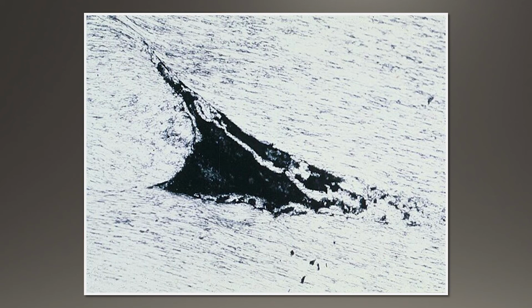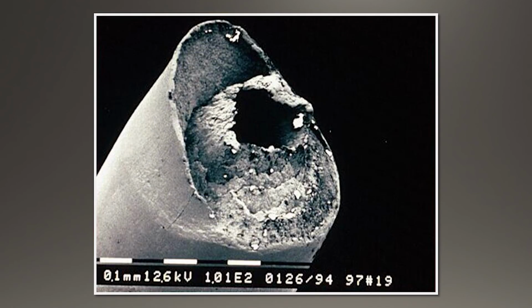This is a cross-section of a wire inside the wire, so you wouldn't see this with the naked eye. But you can see this is the beginning of central bursting taking place. There's a void, that black area is the void, and you can see a cone starting to form. Actually, a crack is forming on a 45-degree plane. So a 45-degree plane in 3 dimensions would be the surface of a cone. But what caused it initially was where it began. And very often, as I said, this takes place in the exact center of the wire where the tensile stresses are the greatest. So here's an example now of a cone taking place.